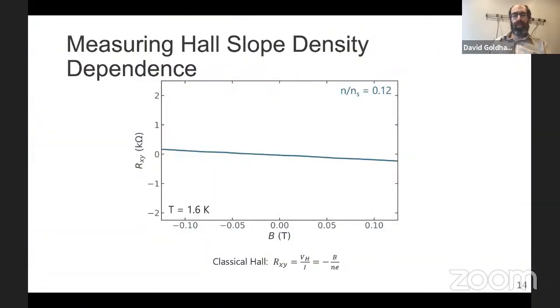All right, so we were just starting to characterize this sample, and my student, Aaron Sharpe, was doing Hall measurements at very low magnetic field, up to a tenth of a Tesla, at 1.6 Kelvin. You can see that there's a small Hall slope. This is at 1/8 filling of the upper band, half an electron added per moire cell. This is at 2 electrons per moire cell, 2.5 electrons per moire cell. You get these small and varying Hall slopes, which allow us to diagnose how we're filling the band.